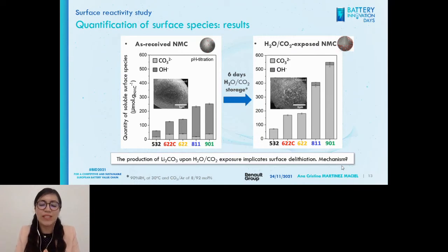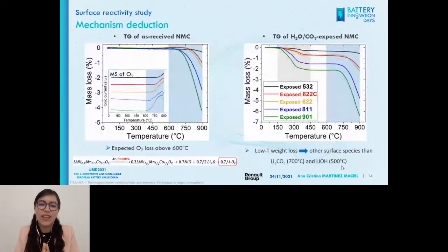So what we did was analyze all of these materials—the 10 of them, as-received on the left and exposed on the right—by thermogravimetric analysis coupled with mass spectrometry. On the left, you can see the result of heating the 5 NMC materials up to 900 degrees.